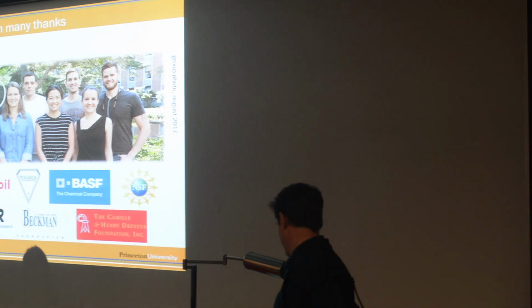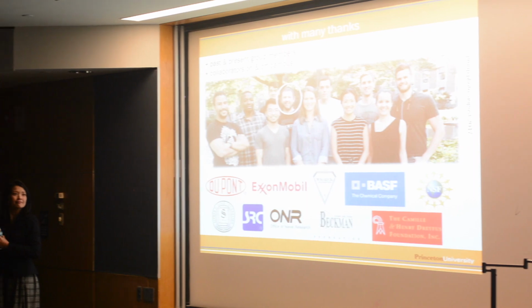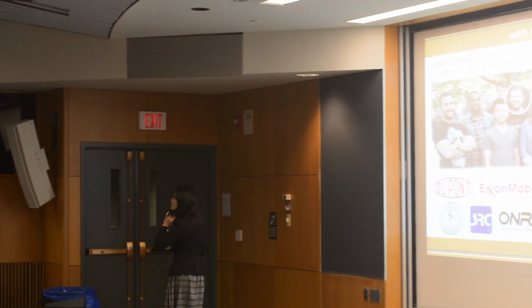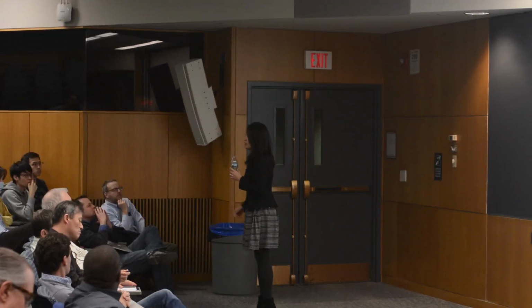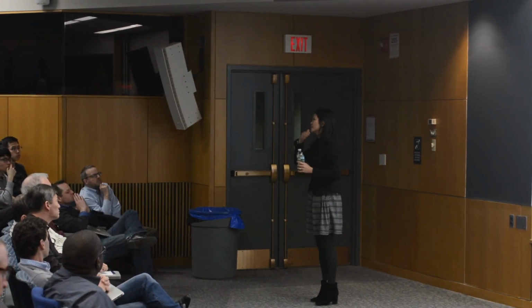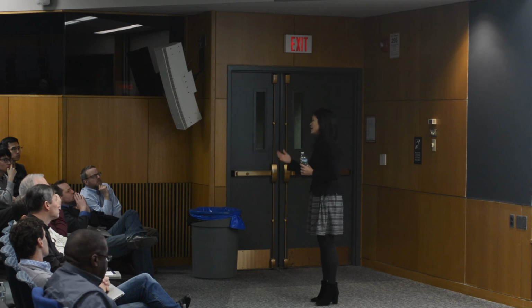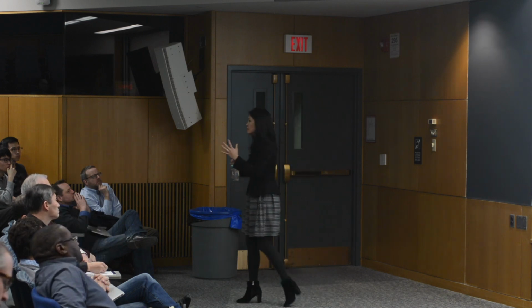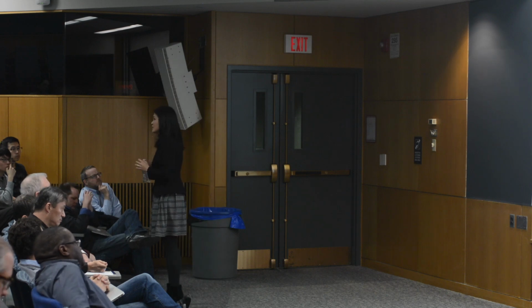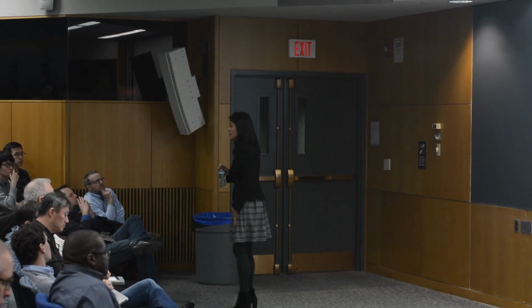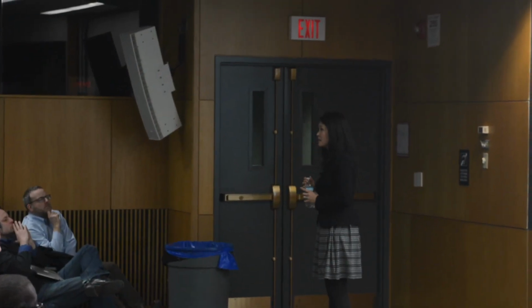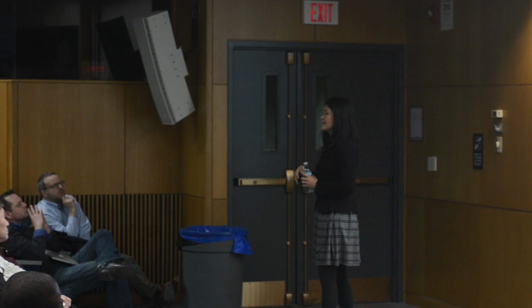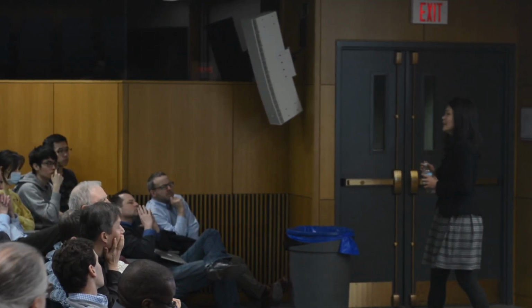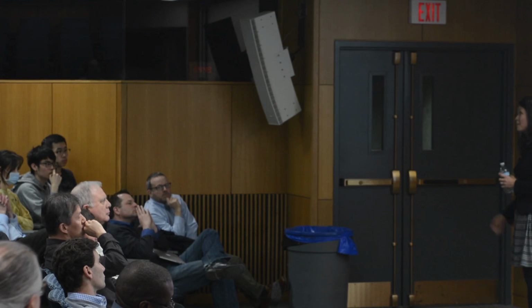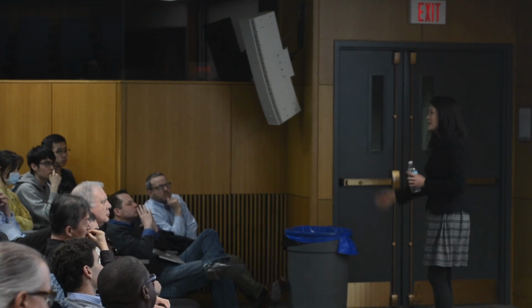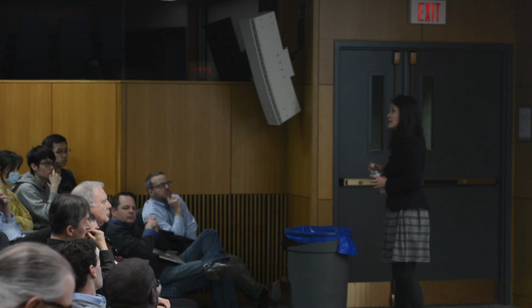So our group did some work on tetracene, and we found that we're able to access the alpha phase when we increase the growth rate. Is growth rate a parameter you consider? Oh, so yeah, that's, again, a different processing route, right? So single crystals are grown at quasi-equilibrium conditions. So depending on what processing conditions you choose, you can favor one polymorph over another polymorph. Yeah, that's completely consistent. I think now the question is, if it sits around, whether it's stable, right? Yeah. And we've not looked at tetracene, so I don't know the answer to that. But if you have the crystal structure, you can look, or we're happy to help you look, and see whether there are short contacts present.